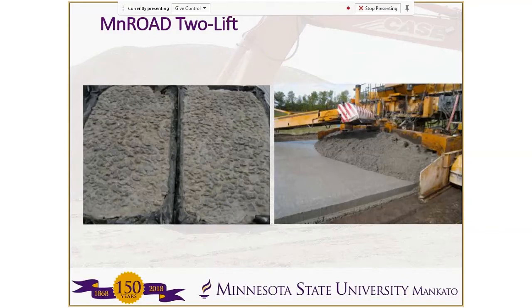And that's just a picture of the construction during the MnROAD test facility. You can see on the right the lower pavement with the recycled concrete has been poured already, and then the top layer, the second lift, is being placed on top of that. And then on the left is just a close-up picture of the exposed aggregate concrete, which was used on the top layer.